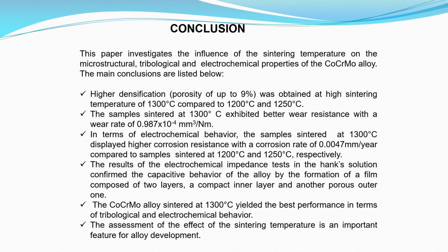In terms of electrochemical behavior, the samples sintered at the highest temperature of 1300 Celsius degrees displayed the highest corrosion resistance compared to samples sintered at 1200 and 1250 Celsius degrees respectively. The results of the electrochemical impedance tests in the Hanks solution confirmed the capacitive behavior of the alloy by the formation of a film composed of two layers, a compact inner layer and another porous outer one.